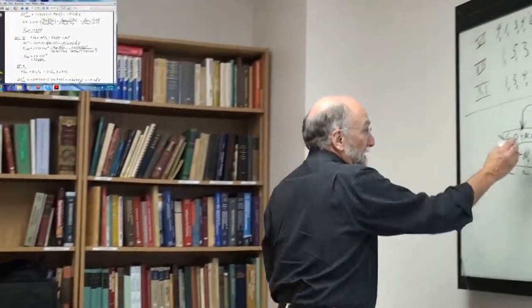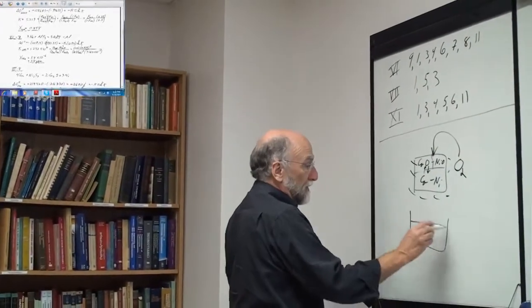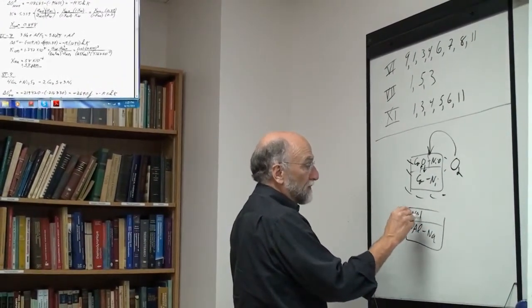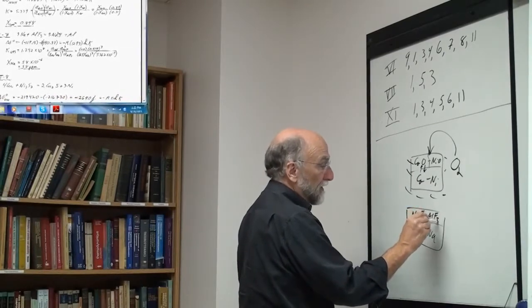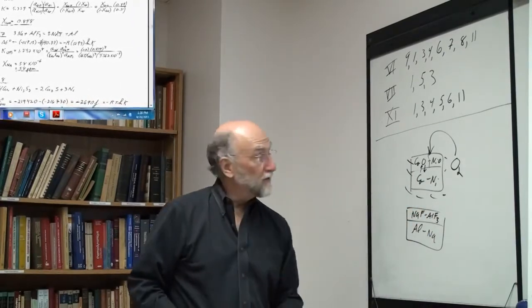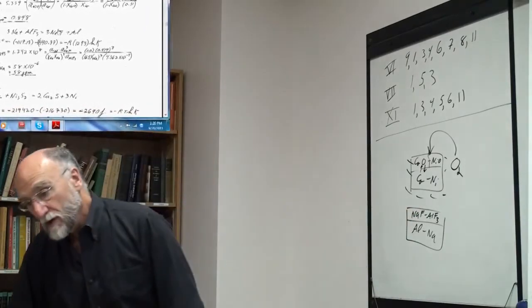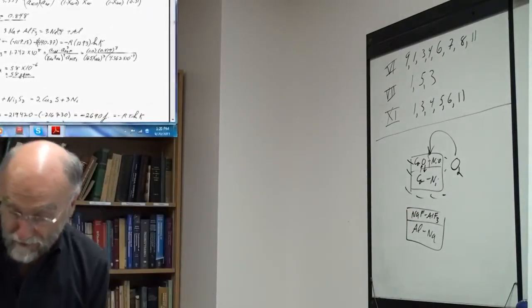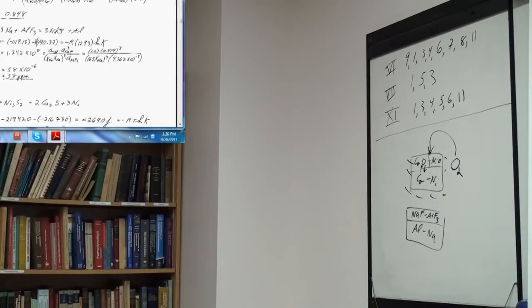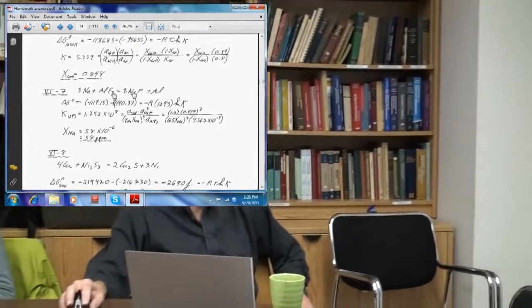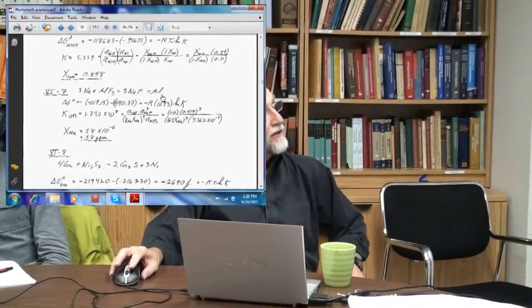So this is again your exchange reaction. You have your two phases. It's exactly the same as this. In your bath, you have two phases. Here you have aluminum with some sodium, and up here you have your cryolite, which is a liquid mixture of sodium fluoride and aluminum fluoride. Even though it's pretty much 3-to-1, it's still one single liquid with an activity of each of NaF and AlF3. And so you write the same thing. There's the exchange reaction. Same thing, the fluoride's in one phase and the metal in the other phase.